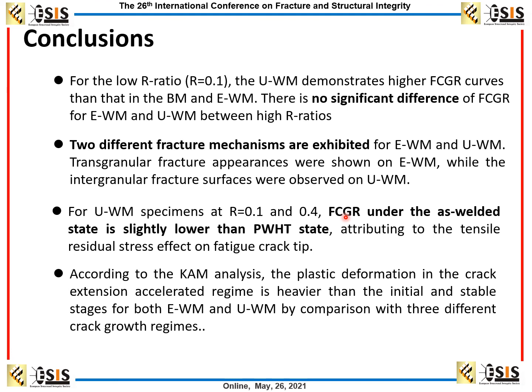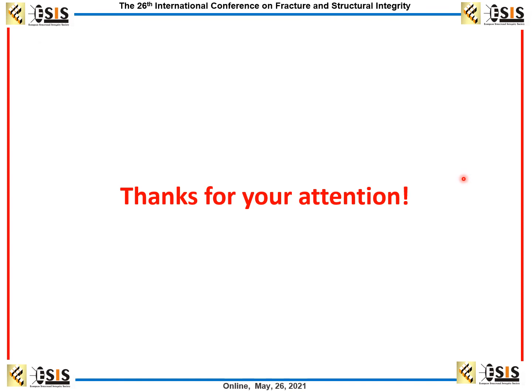The fourth is that according to the KAM analysis, the plastic deformation in the crack extension regime is higher than the initial and the stable stage for both the even matched and the undermatched weldment, by comparison with the three different crack growth regimes. Thank you for your attention.